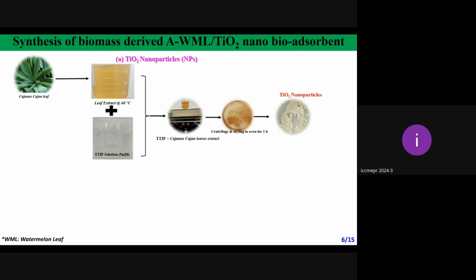Now I am going to discuss the nanoadsorbent I have synthesized from biomass, the AWML-TiO2 nanobioadsorbent. For this, I first synthesized TiO2 nanoparticles. Let us first discuss how the TiO2 nanoparticle is synthesized. For this, an extract of Cajanus cajan leaf, which is commonly in India the leaf of arhar dal, is taken and mixed with a TTIP solution. It is mixed for a period of 8 hours at 60 degrees centigrade, centrifuged, dried, and calcined at 500 degrees centigrade, and we get TiO2 nanoparticles.